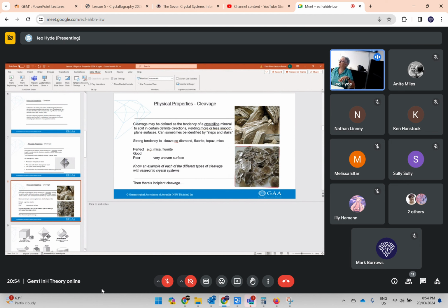So you just get smaller and smaller fluorite octahedra. You need to be able to look with your loupe and decide: is it evidence on anything, on topaz with a plane or whatever? Is that a face I'm looking at, or is it a cleavage plane that I'm looking at? And because it continues to break in one direction, sometimes you'll see iridescence in cracks where it's starting to break, or you might see these little steps and stairs, because it's showing you that it wants to keep breaking in that direction.